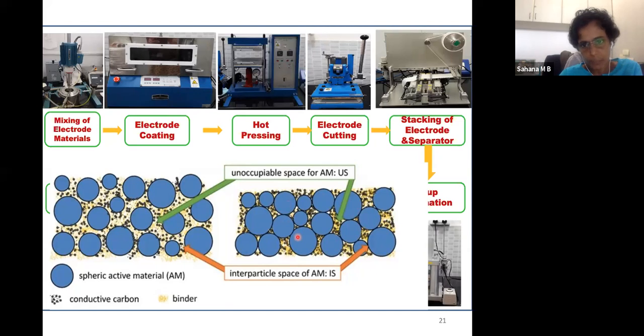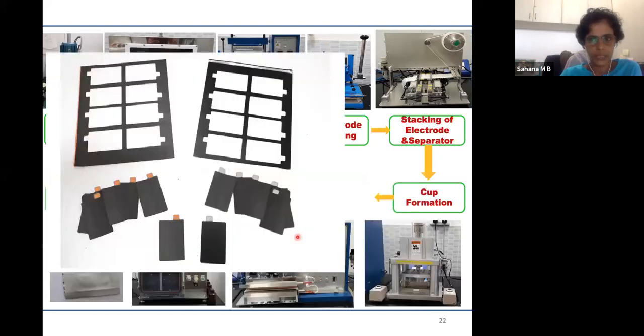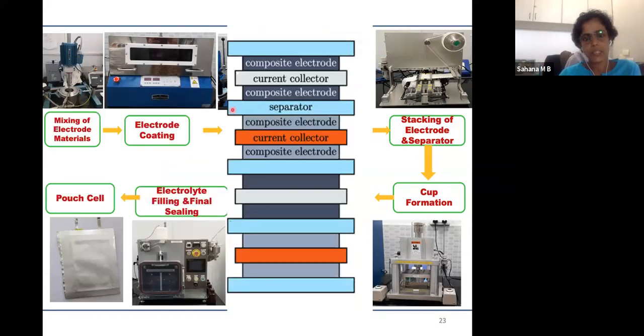Then, for a pouch cell, we need to do the electrode cutting. The cathodes and the anodes should be cut in such a way that the sizes are what we desire, and there should not be any burrs at the sides of the electrodes. What happens is the burrs will always give you a short circuit. They can penetrate through the separator and the cell can go bad. And the next step is basically stacking of the electrodes.